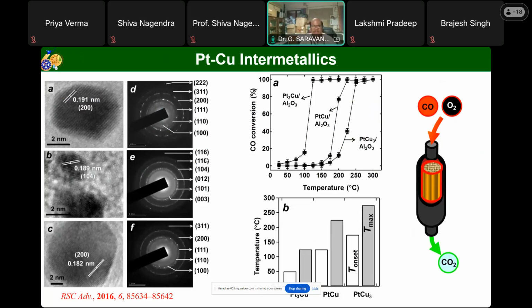So we have done Pt-Cu combinations with various types of intermetallics. Here, all at 5 weight percent loading, PtCu3, PtCu and Pt3Cu, we have done the model CO oxidation. When you compare these catalysts, although they have the same loading weight, platinum at 5 weight percent, this catalyst shows much higher activity. Please note that the same loading weight, when you achieve different intermetallic structures, gives different performance.